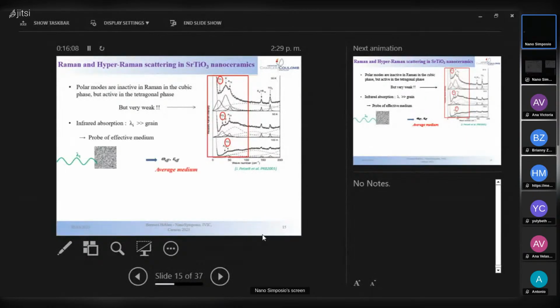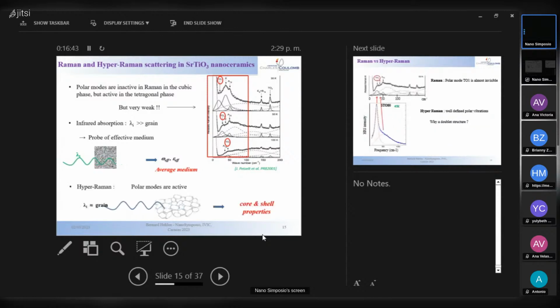So we can use infrared absorption. But the problem with infrared absorption here is that you probe the sample at a wavelength which is much higher than the grain size. And so what you see is an effective medium. You don't see the details of the grain because you probe your sample with a wavelength which is much higher than the grain size. Okay, so this will not help to see the core and the shell. So infrared you can forget. And so the only remaining spectroscopy is hyper-Raman, because here the wavelength is about 1 micron, which is comparable to the size of the grain.